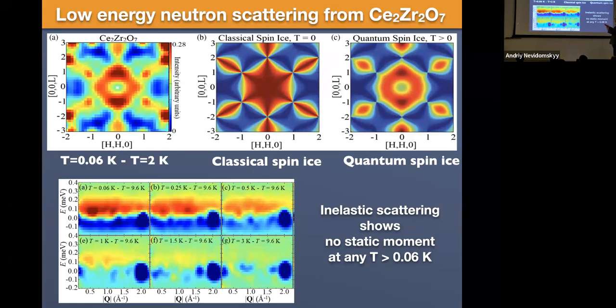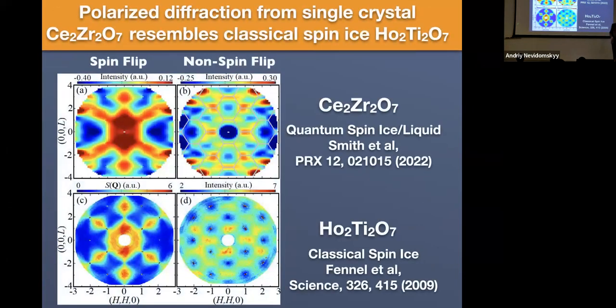But this sort of pattern is very similar to what's imagined and what's calculated actually for the classical spin ice problem, which has now been around for the better part of 25 years, so very good calculations for it. And this is one version of a quantum spin ice problem, which has a structure factor that looks like classical spin ice, but it's a little bit fuzzier, as you might have guessed for a quantum version of the same problem. So at any rate, this sort of diffuse scattering pattern is somewhat of a fingerprint for this type of quantum disordered ground state.